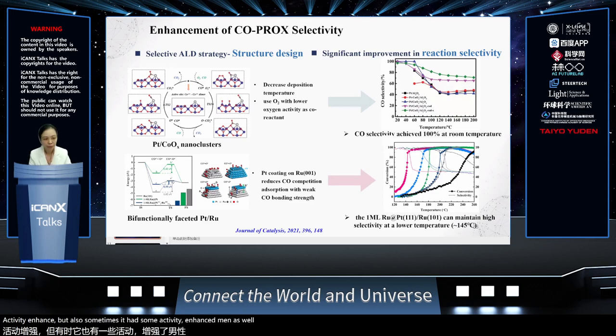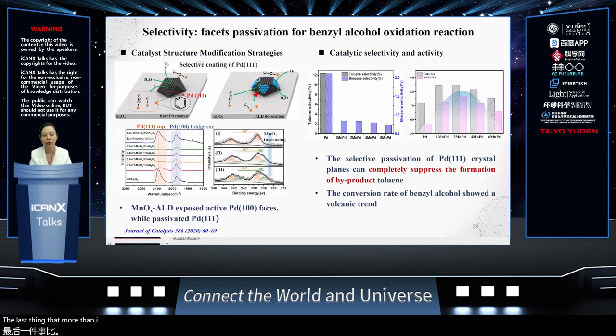The last example that I want to show is that by utilizing this kind of inherent phase selective deposition, we'll be able to cover a certain phase of this palladium, like palladium 111 has been covered. Then we leave the other phase completely open, and we will be able to obtain a very good selective benzyl alcohol oxidation reaction. We don't get too much of the byproduct when we get really pure end products.